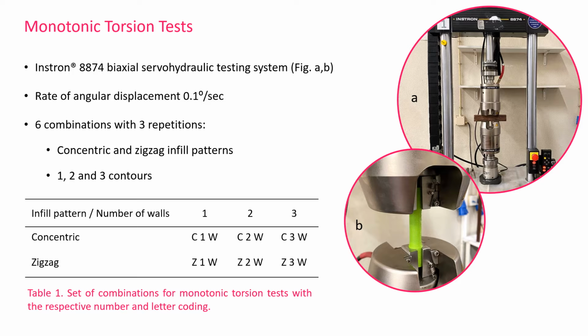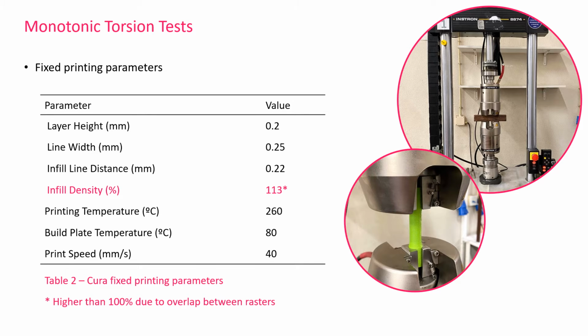To study the mechanical properties of ABS specimens, a set of 6 combinations with 3 repetitions was developed, and concentric and zigzag infill patterns were assessed, varying the number of contours between 1, 2, and 3. Table 1 shows this first set with the associated number and letter coding for each case. The remaining printing parameters were kept constant and are listed in Table 2.